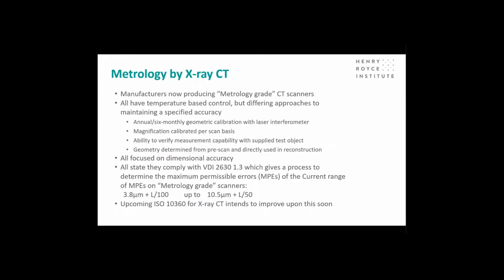Metrology by X-ray CT is an emerging tool, and manufacturers can now produce metrology grade CT scanners where the temperature is controlled, where you have geometric calibration with laser interferometers, and the magnification can be calibrated using special calibration samples prior to scanning. And it gives you the ability to measure certainly to within a few microns the dimensional accuracy of your component. And there are emerging standards for qualifying those measurements.